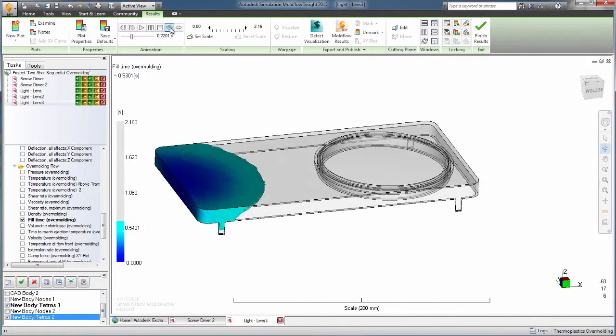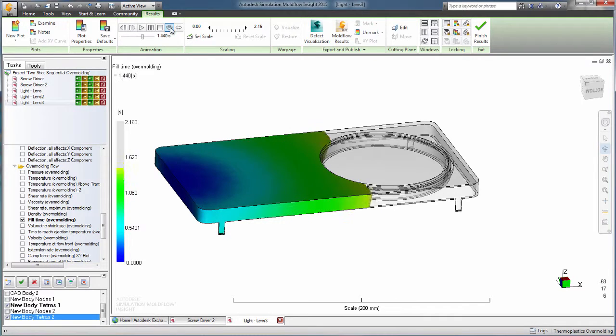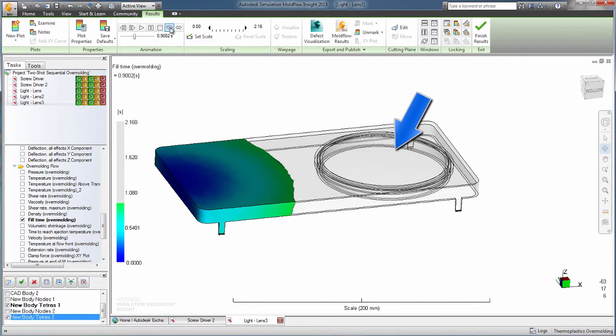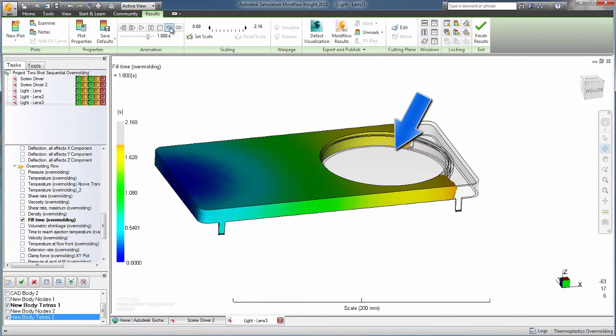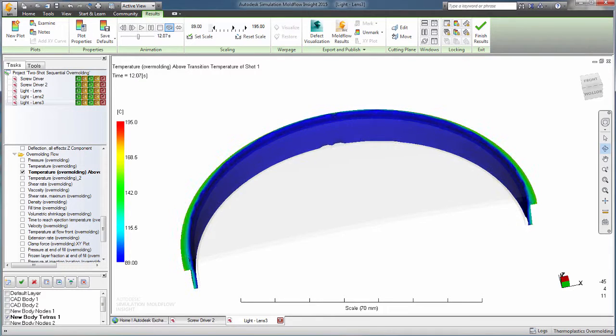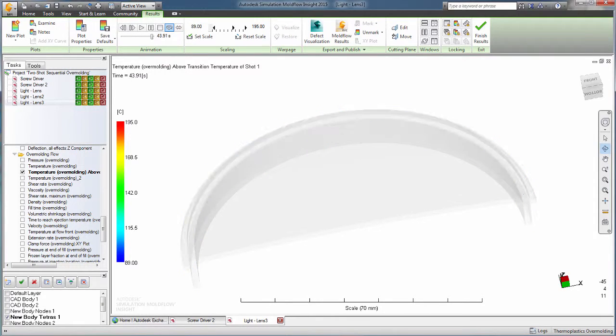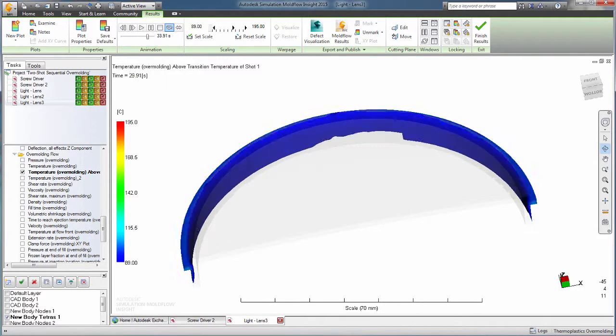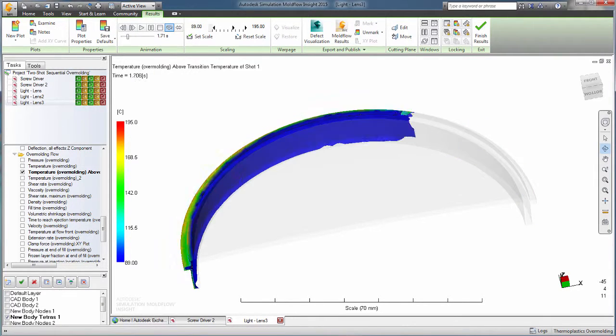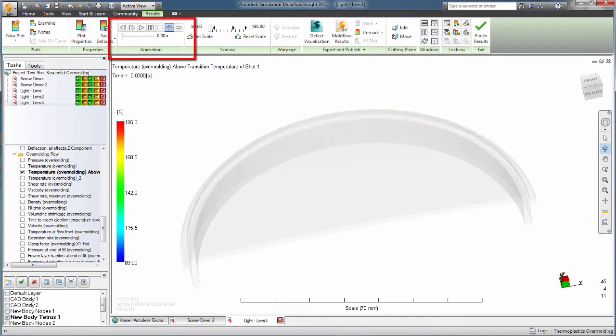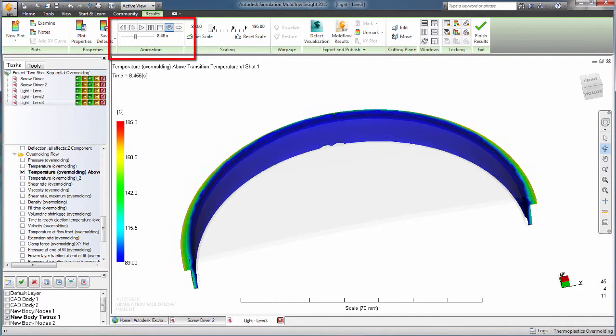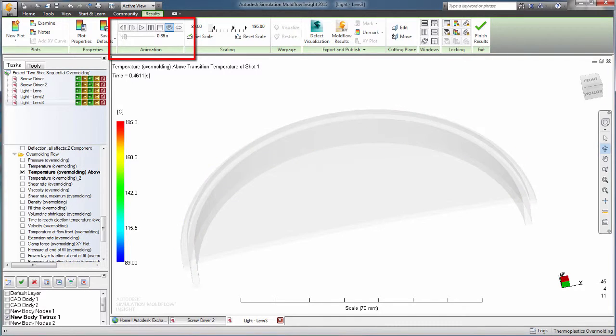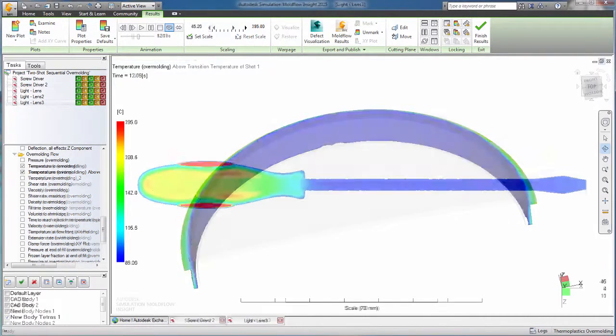Or we can see what happens to the temperature of the first shot as the second shot enters. With this rear car light cover, we are looking at the first shot and plotting the temperature above its material freeze point as the second material is injected. This result indicates that there is some re-melting of the first material occurring.